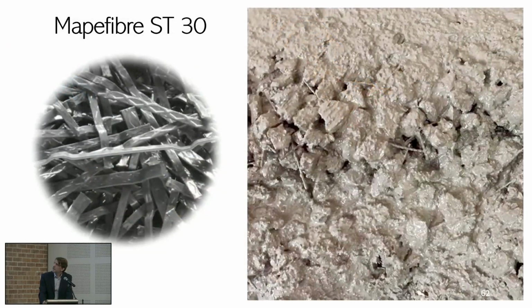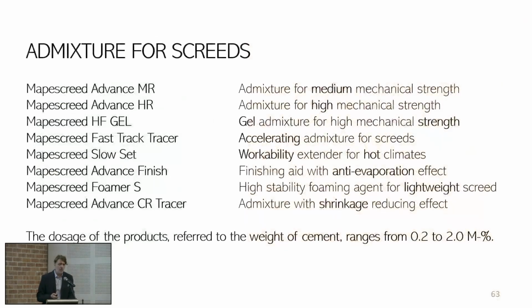To reduce the formation of cracks, we can also add into the screed some fibers, metallic or polyester fiber, something that is going to reduce the shrinkage or bear the shrinkage of the concrete. Or we can adopt some additives. There are some special additives in a very low dosage, 1% of the weight of the cement, that can provide you some reduction of the shrinkage of the Portland cement compounds.